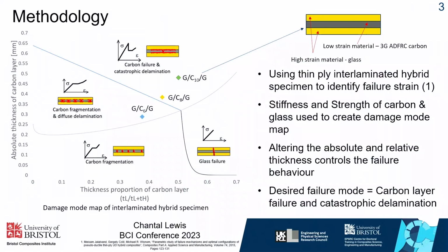So the damage mode map here is shown, which tells you the 4 different failure modes that are possible for these specimens. In order to be able to detect the failure of the inner carbon ply, the specimen needs to be designed in such a way to achieve the failure mode of carbon failure and catastrophic delamination. In this region, the failure of the carbon will show as a sharp load drop in the stress and strain curve, so it'll be easy to detect, especially with the glass material on the outside, so you can kind of see through the specimen and see where the carbon fails.